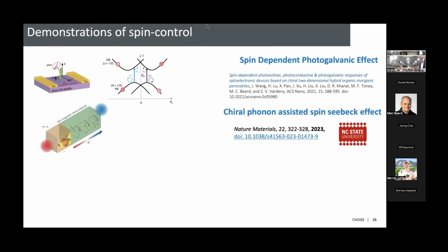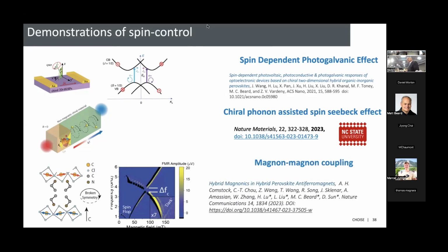You can also use phonons. This is work from NC State, Dali Sun, it's in our center. But anyways, if you induce a temperature gradient across this chiral film, you can drive a chiral phonon into a proximal metal here, and you convert this phonon into polarized spin. Okay, you can do magnon coupling as well.